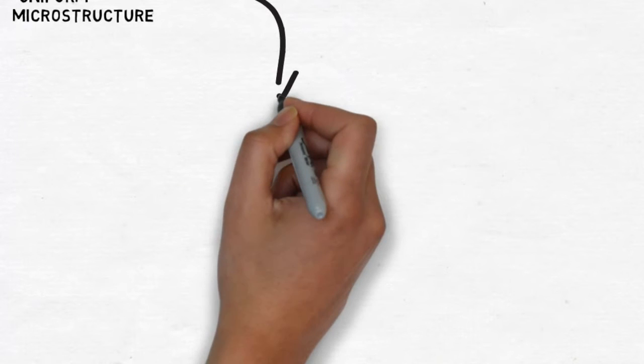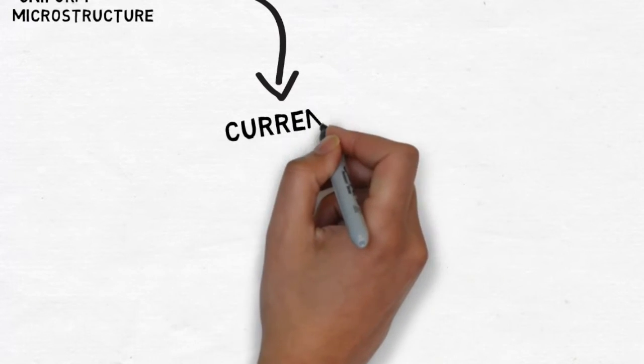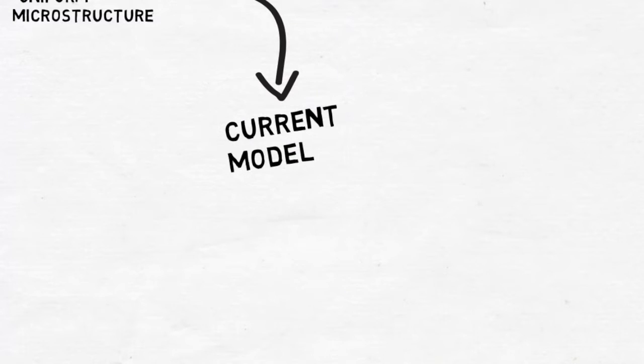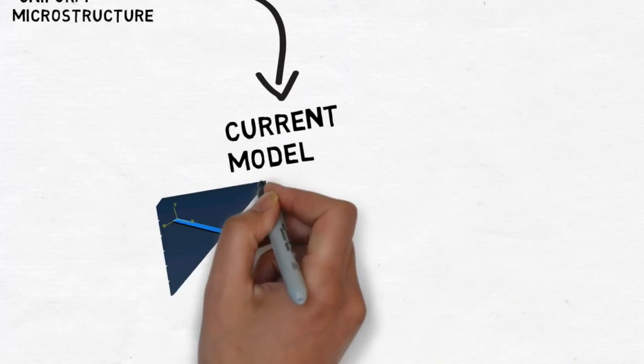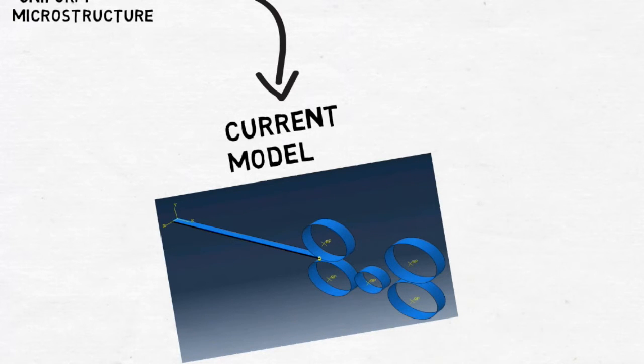We moved on to another design that aimed to utilize the horizontal shear effect resulting from transverse shear and bending. This shearing effect produces shearing stress in the middle of the workpiece, while the rolling shears the surface. This was achieved by having a normal rolling process, but with a free-to-rotate roller in between that rises to induce the bending and subsequently induce shear.